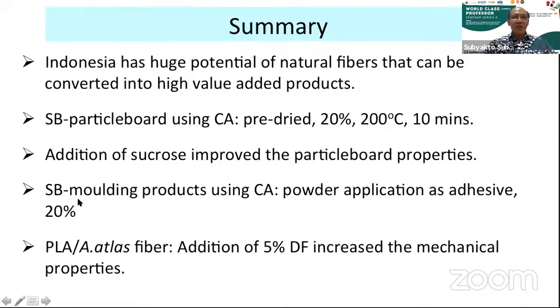And if we make a molding from sorghum bagasse, the powder application can act as adhesive, and 20% the citric acid content. And for this PLA Attacus atlas fiber, addition of 5% degum fiber increases the mechanical properties.